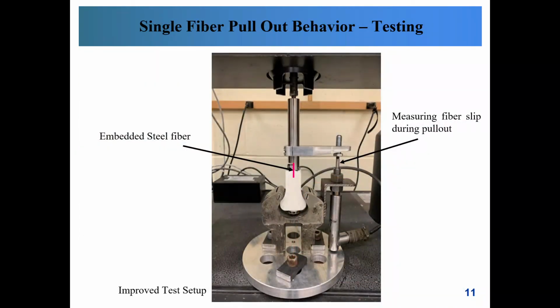In preparation for the investigation of fiber reinforcement efficiency, an improved single fiber pull-out test setup has been developed. You see here highlighted in red the illustration of the embedded fiber. A load cell measures the pull-out load while the LVDT measures the fiber slip. This test setup has successfully been tested, and more tests will follow to characterize the bond between fiber and UHPC matrix.